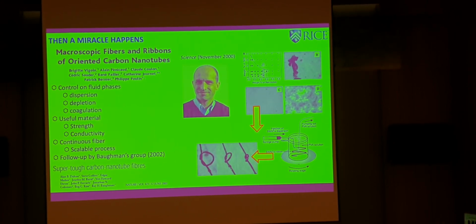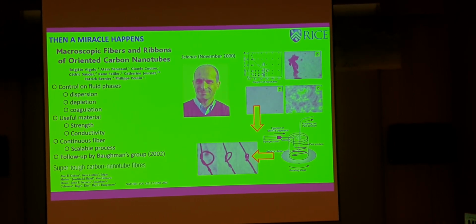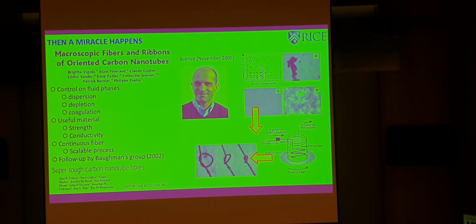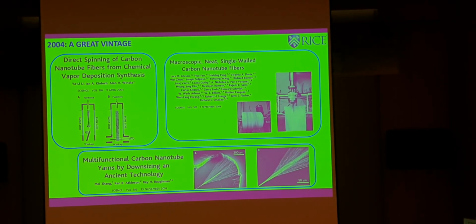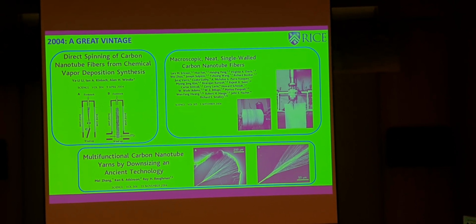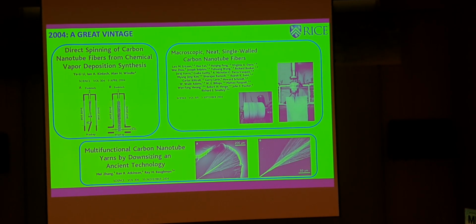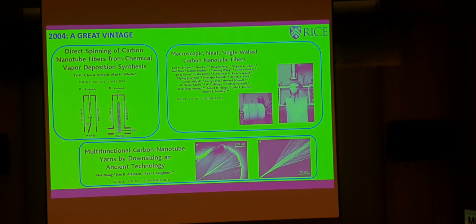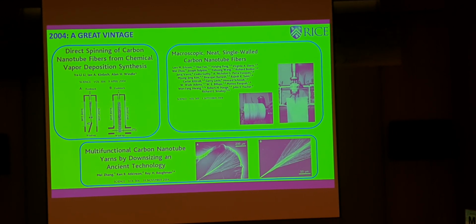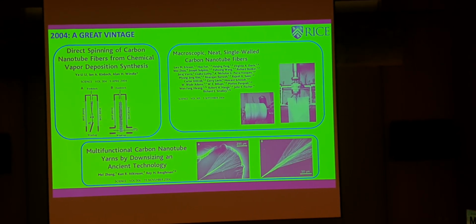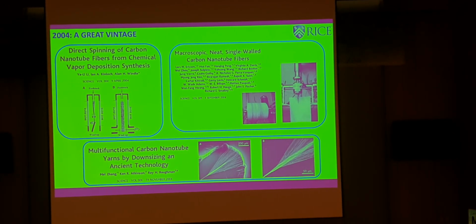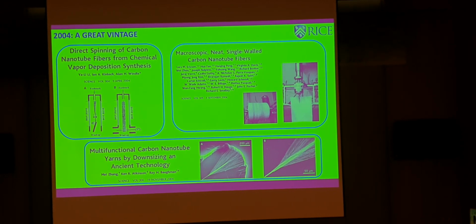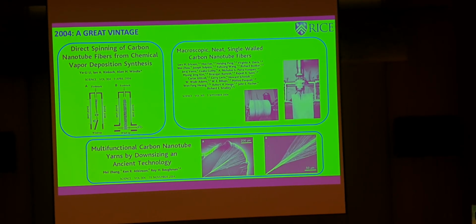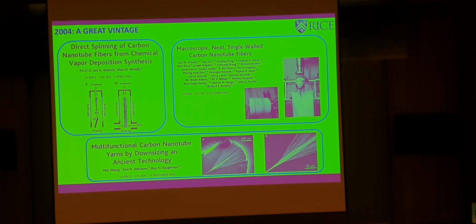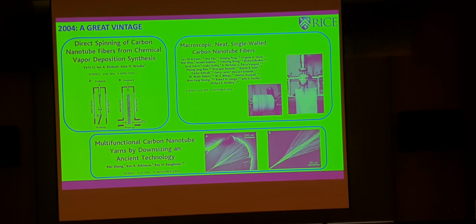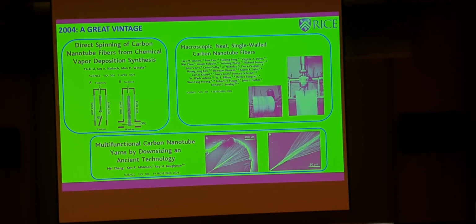And Ray Baughman and his group followed up with a variation on the theme after a couple of years. And then nothing happened for a couple of years, or it looked like nothing was happening, and then there was a great vintage of 2004, where essentially all the methods that we know now for making carbon nanotube fibers were published. I don't think there's really anything that has taken on a large scale that's outside either the Poulin method or variations of it. So Alan Windle was the first to publish direct spinning by pulling the material directly out of the reactor. Our group, with Rick Smalley still alive at the time, did the spinning from liquid crystalline solutions in acids, and Ray Baughman did the spinning from arrays.